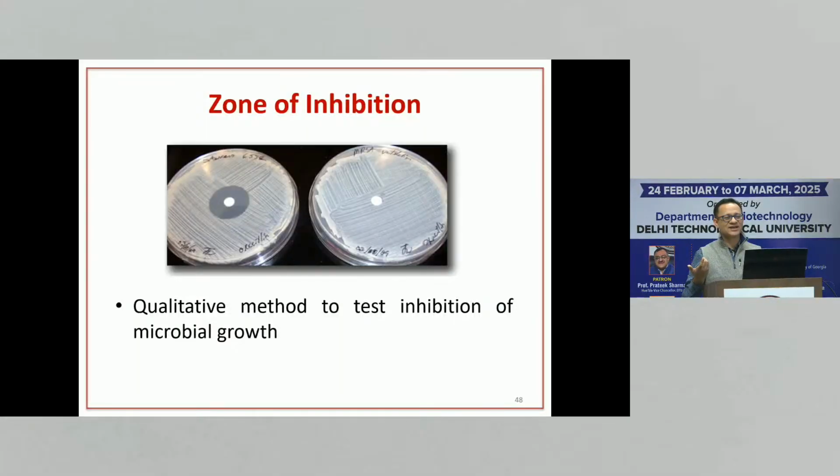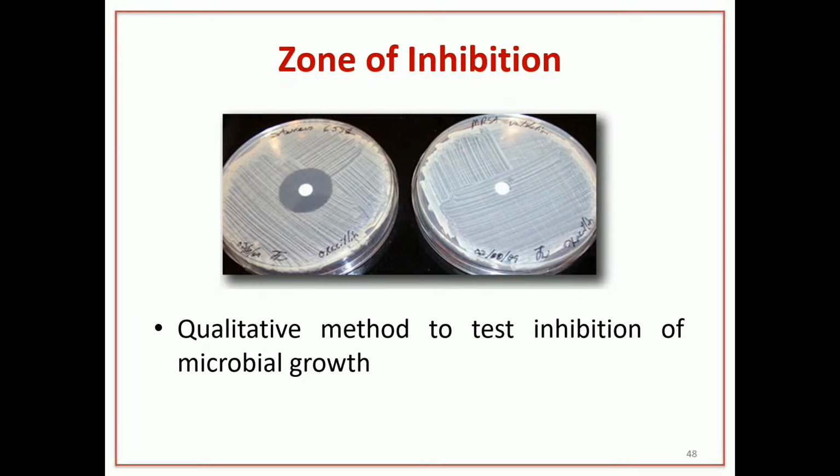SEM can be good supporting data to that. But if you just show SEM, a lot of times reviewers and scientists don't like it, and I won't like it either, unless the study was done blinded. One person did the catheter study, gave it to their lab mate and said, here are the two surfaces, I won't tell you what is what, do SEM for me. Then the other person looks at the whole catheter surface, different spots, and shows a representative image of the whole surface. Now that can be an honest way to report SEM. Okay, but there is one more problem with SEM. Who can tell me that?